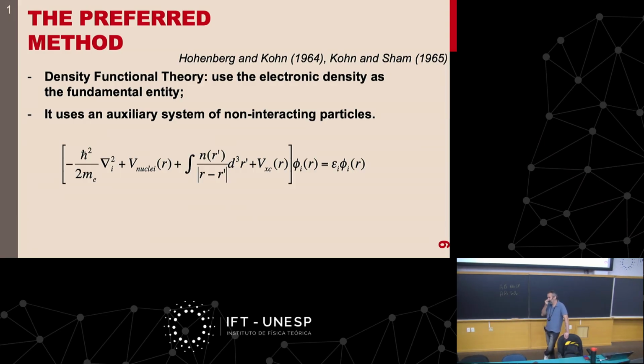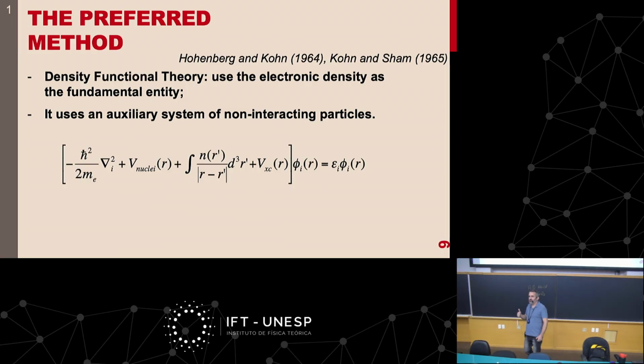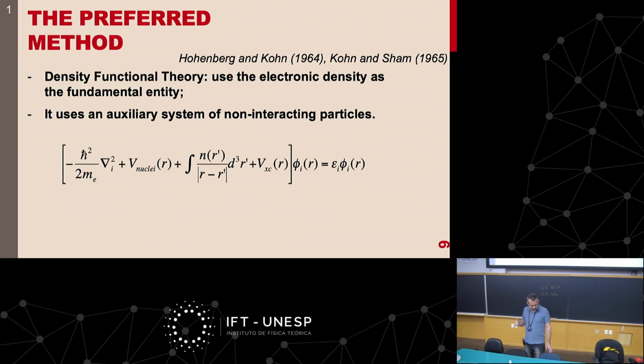Some more questions? Well, actually, just a curiosity. What is the conclusion about the direct or indirect band gap? Our conclusion is the following. First, symmetry is very important. So the first important factor is symmetry, and then the second important factor is the existence or not of d electrons.